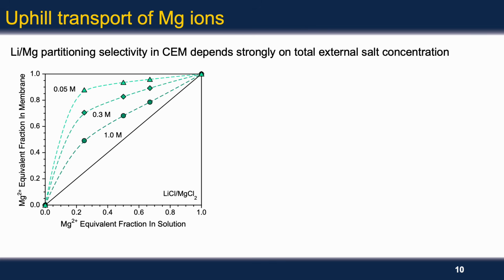To explain the concept of uphill transport, I'll bring up another equilibrium curve, but in this case I'll show the magnesium equivalent fraction in the membrane and in the solution. This plot shows experimental results for 3 different experiments that were performed at different total salt concentrations from 1 molar to about 0.05 molar. The key takeaway here is that as the concentration of salt in the solution decreases, the preference for magnesium sorption by the membrane strongly increases.